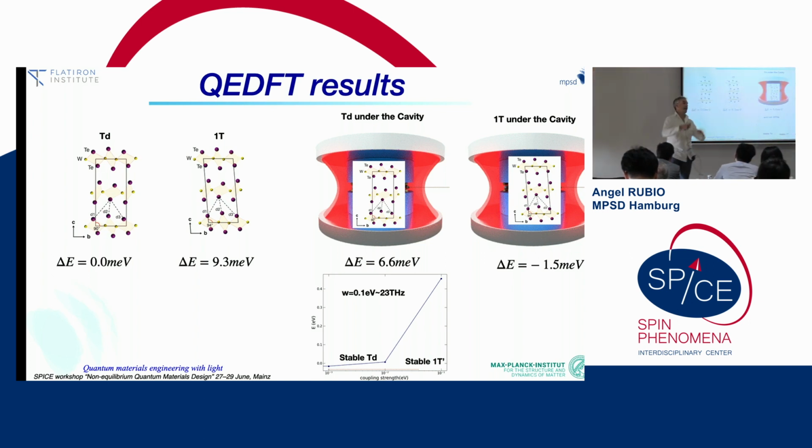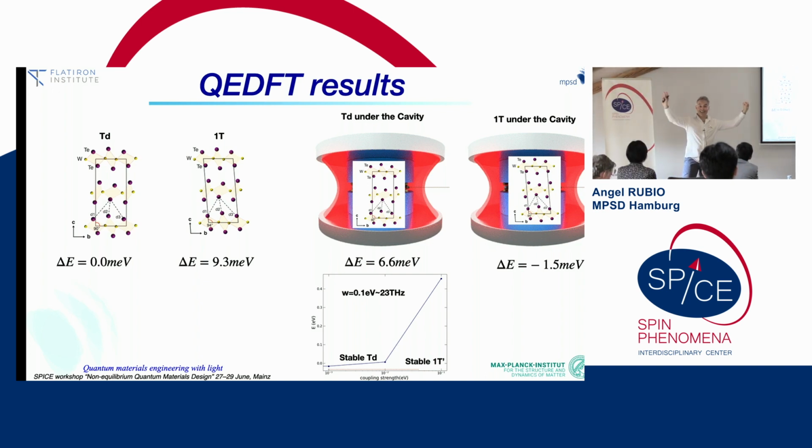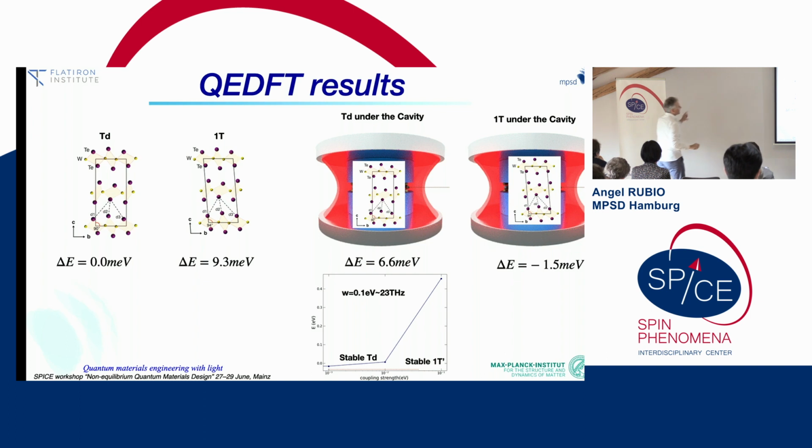Then automatically, what it's doing is that the system undergoes a shear mode. And this is eventually something that you could see. In this case, you go from Weyl to trivial metal. Maybe that's not interesting, but if you were doing it in the monolayer, you would go from Weyl to topological insulator. And this is automatic, and the only thing you need is the cavity resonance in the terahertz regime. Then we can discuss why. If you put it at high frequencies, it will not work.